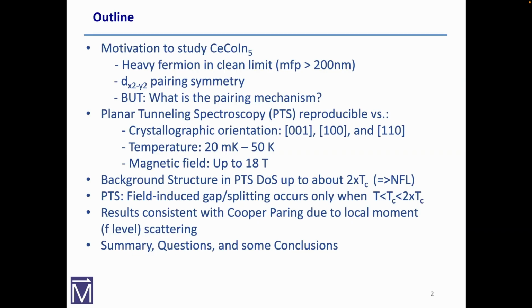I'll let that go. Why we're studying cerium cobalt indium-5: apparently it's the most studied of all the heavy fermions. It's an incredibly clean limit, with a really long mean free path and coherence length. We all know it's a dx²-y² pairing symmetry. If you disagree with me, I've got the data to prove it. But we do not know what the pairing mechanism is. Just knowing what the order parameter symmetry is doesn't really tell you anything about the pairing mechanism.